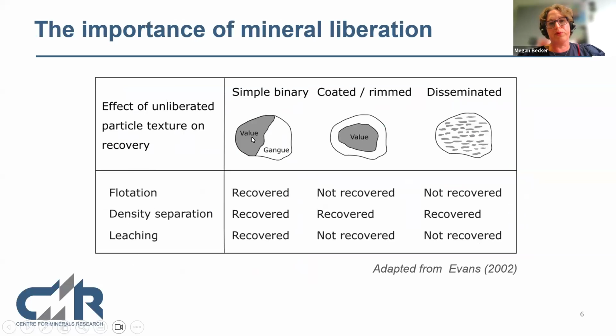So in this example, we have a valuable particle 50% and gangue is 50%. The gray is 50-50. And this is a simple binary texture. This is a coated or rim texture, and this is disseminated. If I'm preparing it for something like flotation, that particle, the chances are it will be recovered. If it's a rim texture, so over here, your bubble will never see this dark phase, and so it's unlikely to be recovered. And the same here, not likely to be recovered.